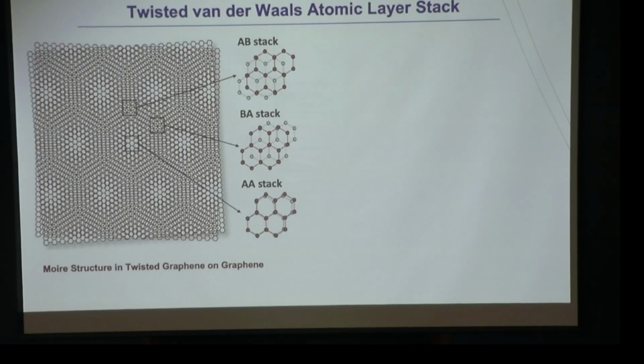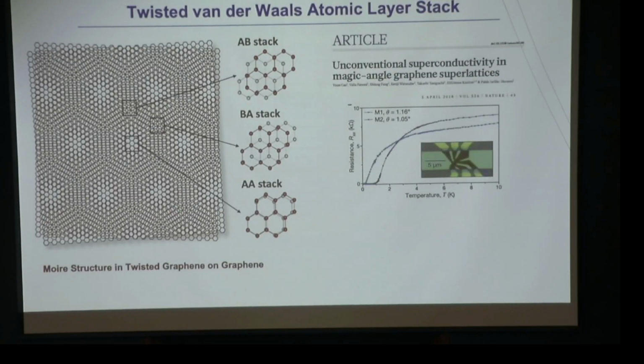Utilizing this type of quasi-periodicity, a few years ago a group led by Pablo Jarillo-Herrero at MIT discovered something really shocking and sensational. They put graphene at the so-called magic angle of 1.1 degrees, and what they saw is that graphene becomes an insulator, the so-called correlated insulator. Doping that correlated insulator, they started to see superconductivity. That was completely unexpected, except that there was a paper 10 years ago on flat bands. But this is another interesting way that serendipity works. Few people expected that this could happen. No one, including myself, believed that this could happen.